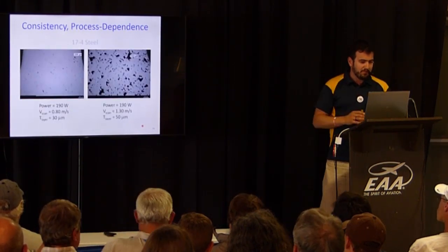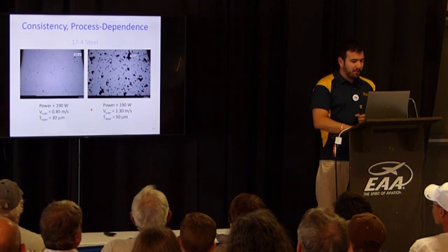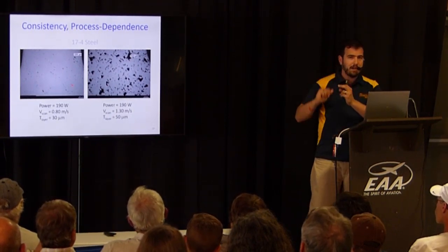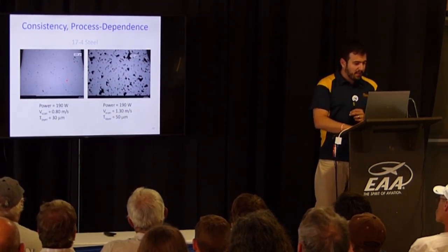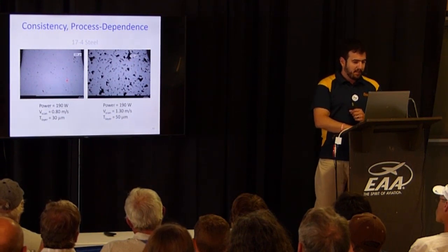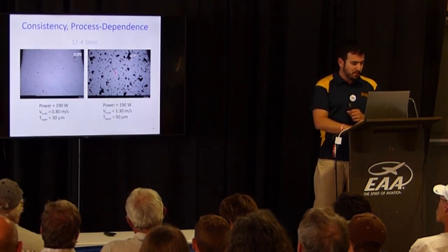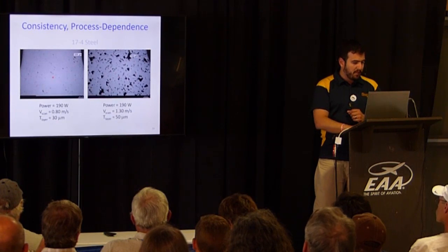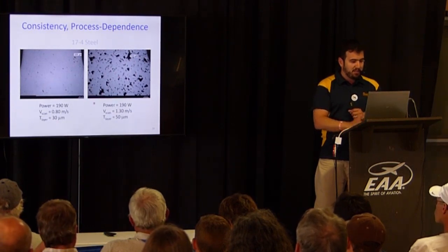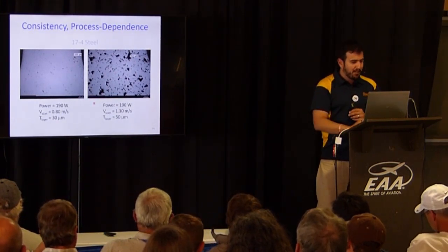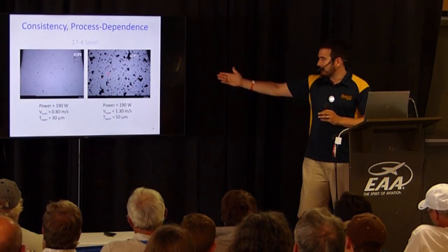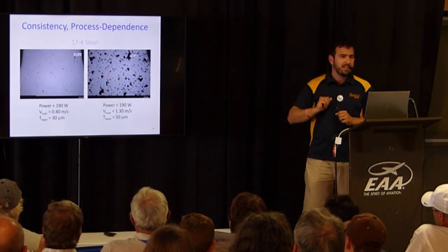Here's another one, right? Same 3D printer, same material. They're both at 190 watts, the power of the energy beam. This one's moving at 0.8 meters per second. This one's moving at 1.3 meters per second. And the thickness of the layer went from 30 microns to 50. So you change a little bit, but not much, but the difference in the material is drastic. You get all kinds of pores and things in here by just changing it a little bit.